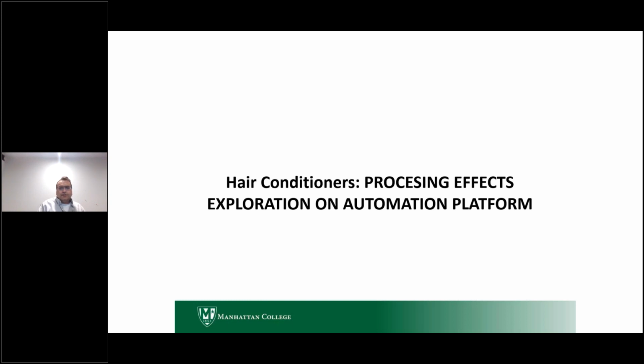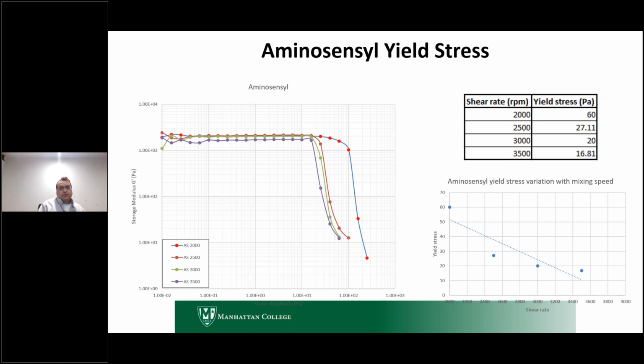So we wanted to explore that by changing the processing variables on the automation platform. So here in this case, shear rate. One of the things I was saying is that these systems build up very strong lamellar gel structures which are very strongly connected. They're interconnected, okay? And that interconnection gives rise to yield stress, right?